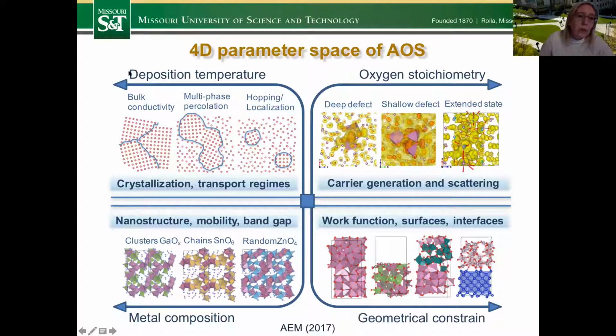So first we will talk about deposition temperature and how that affects crystallization and transport regimes, how we can go from bulk conductivity to multi-phase percolation to hopping and localization. This is probably one of the major parameters, but of course that's not the only parameter that controls the properties. Metal composition affects the nanostructure, mobility, band gap, work function. So again, that is what is expected. And so we need to separately look at the metal composition as well as the deposition temperature.